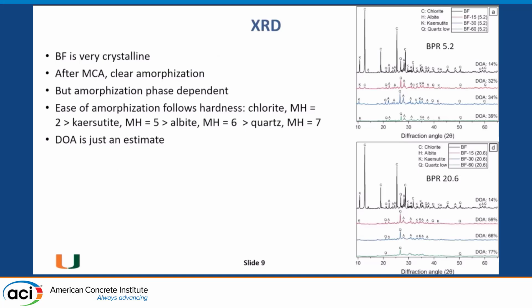So on the other hand, the XRD results are, to me at least, a little bit easier to interpret. So we haven't done internal standards yet, so we kind of estimated the degree of amorphization using a few different approaches. And essentially what you see very clearly is after mechanochemical activation, the peaks drop. And I realize just the drop in the height of the peak is not necessarily a quantitative indicator, so take it with a grain of salt. But in all cases, as you continue grinding, the peaks drop, drop, drop.